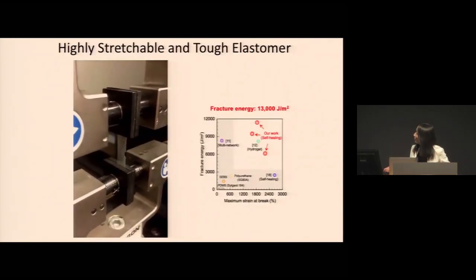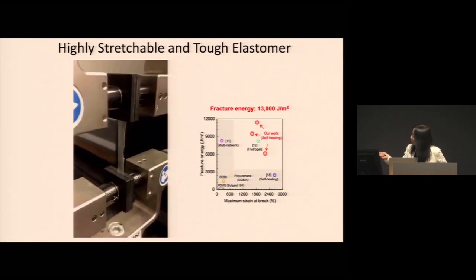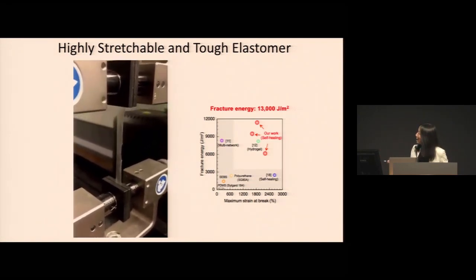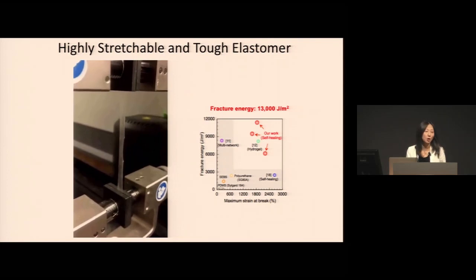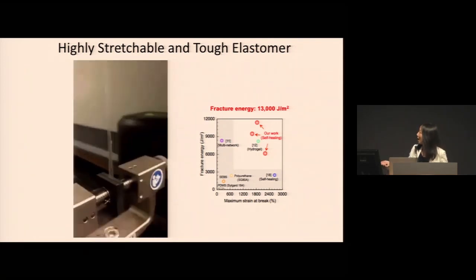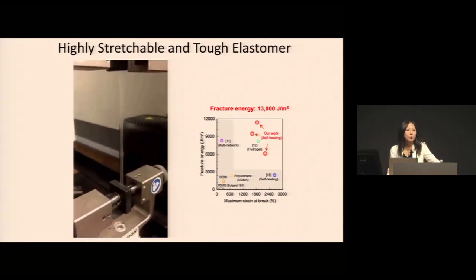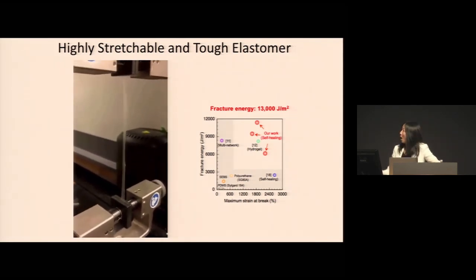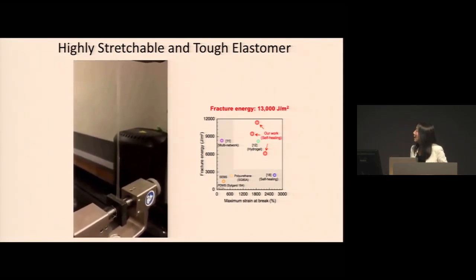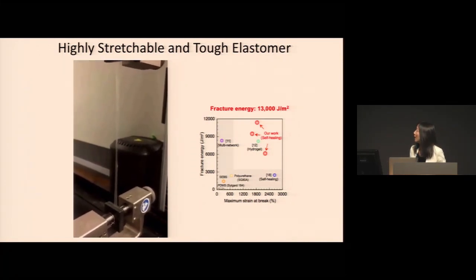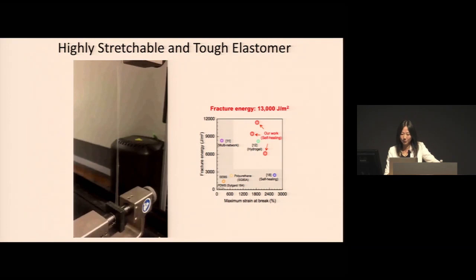So indeed, using this design, you can see we introduce a defect intentionally, but this material can still tolerate extremely high strain, being stretched to more than 12 times its original shape without forming any cracks. And it turned out this type of design actually can give us self-healing materials that are both stretchable and self-healable, with the highest fracture energy that's been realized for any self-healing elastic material.